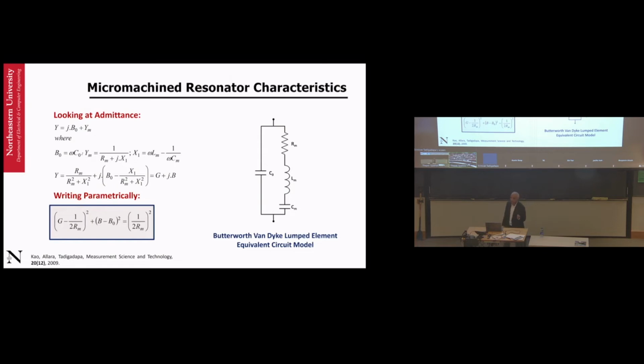But the problem with it is that, as I said to you, it was not possible to make it in thin film form. So I said to myself, well, in that case, we'll develop a fab process. Now, as it happens, in that time, silicon's etching rate was going through the roof. It started at like half a micron, maybe even a few nanometers. Suddenly, by the 1990s, we were talking of etch rates for silicon that went into 20 microns per minute. A typical silicon wafer, for those of you who don't know, is about 400 or 500 microns. So that means we can actually realistically etch a silicon wafer.